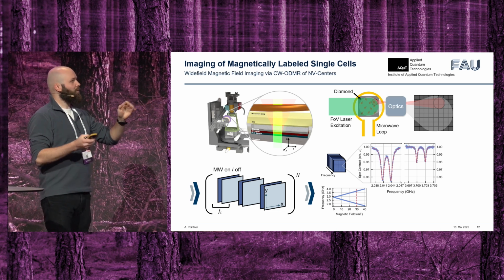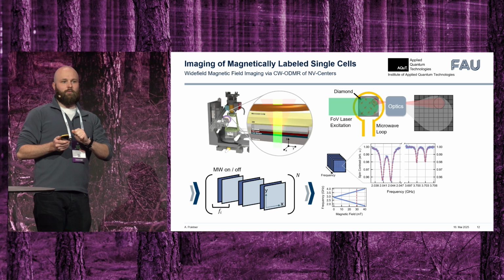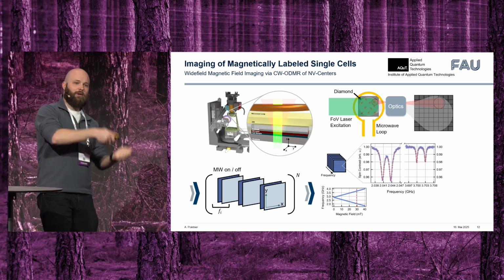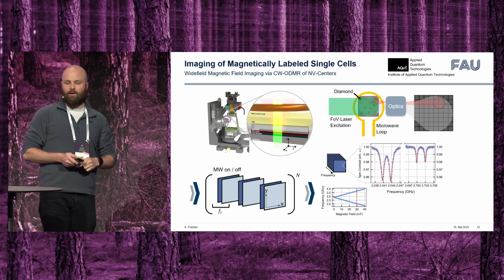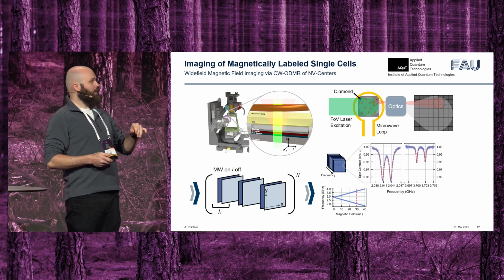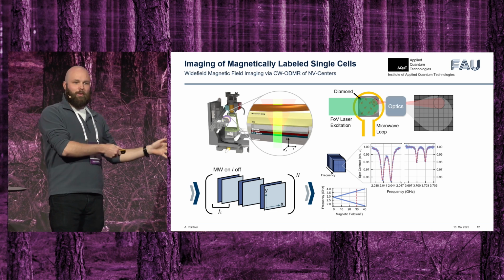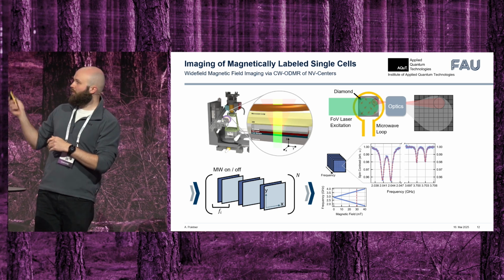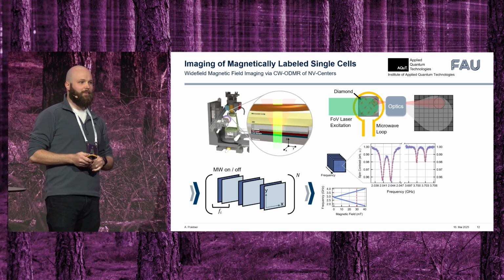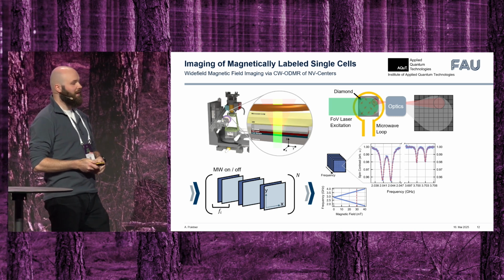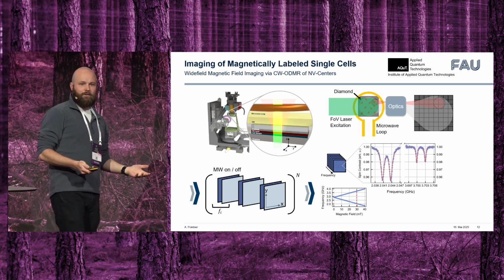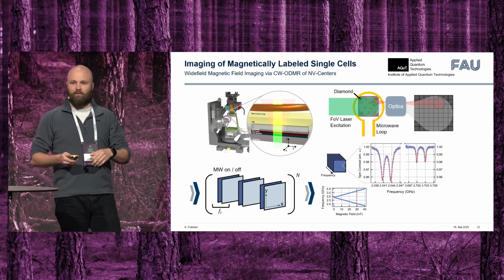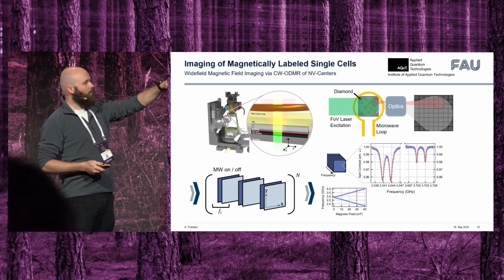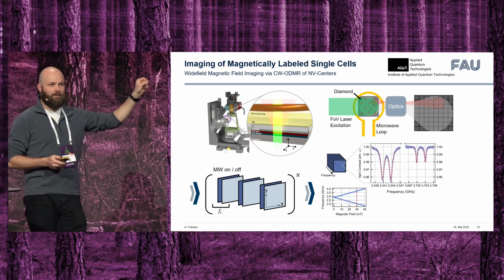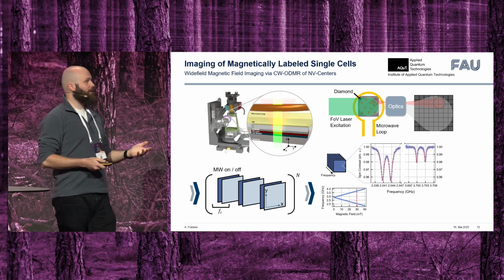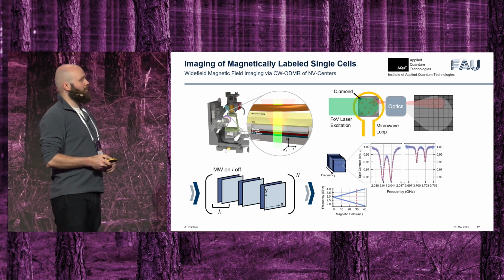And this happens when our microwave is exactly resonant with the NV center's spin, and it starts flipping the spin population into the other dark state. And the nice thing is, since we know about the theory of the NV center, we know that the spectral position of these minima, of these dips in the fluorescence signal, is linearly dependent on the magnetic field. It's something called the electron-Zeeman effect. And by now detecting where these resonances are for each pixel of our camera, we can infer a magnetic field for each pixel of this camera.